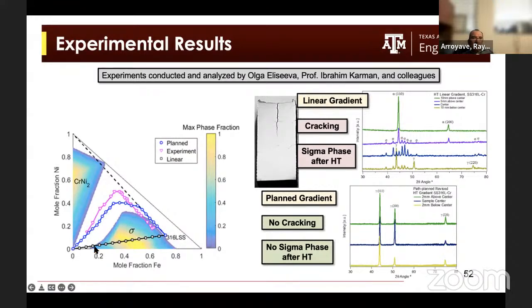And of course, what we found when we tried this path is that the sigma phase, which is really bad in steel alloys, is prevalent for much of the path. And then what happens when you try to print this naive path, you actually have cracks because you have the formation of these very brittle phases.